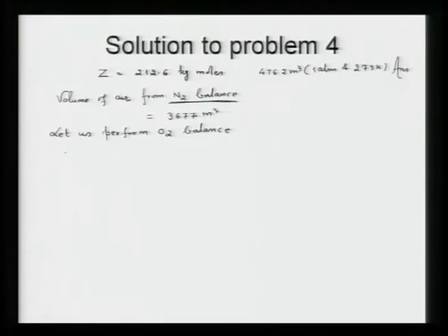So, let us first calculate the oxygen moles in gas. That will be equal to 212.6 times 0.26 upon 2 plus 0.13, which is 55.3 kg mole. This is the total oxygen available in the gas, but mind you, this oxygen consists of oxygen from air as well as oxygen from the charge. So, we have to subtract that oxygen from the charge.